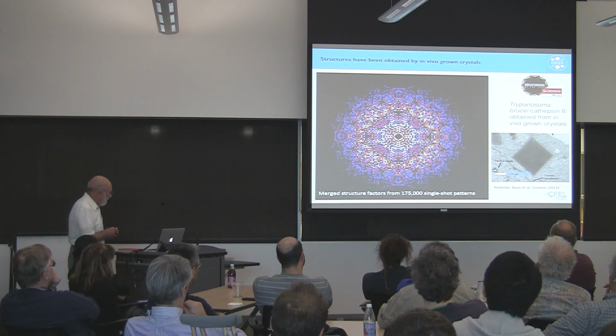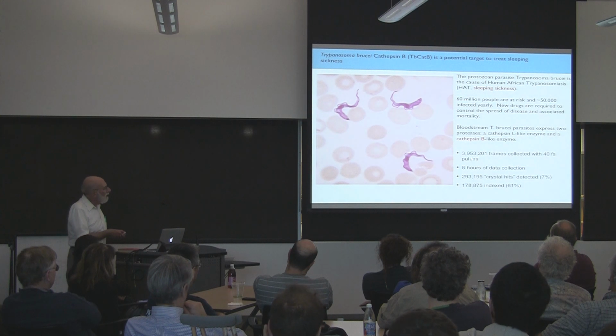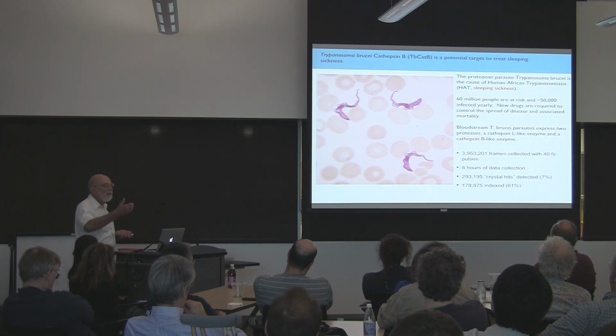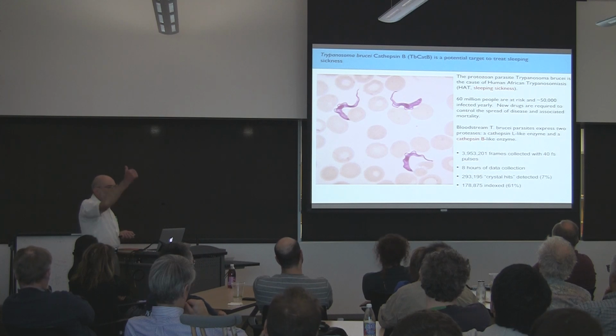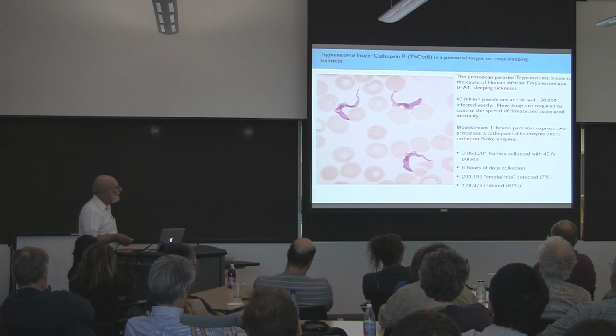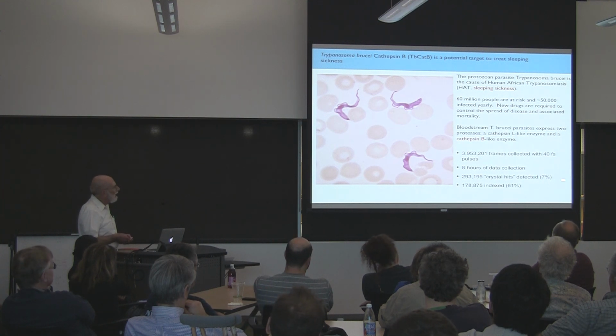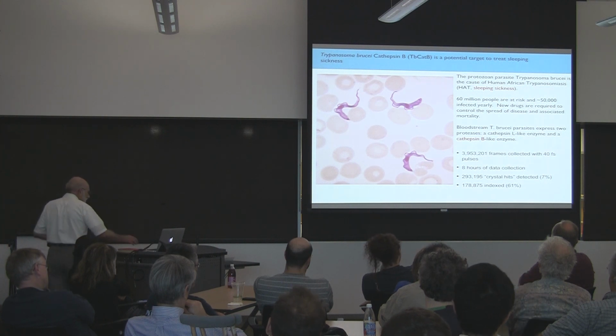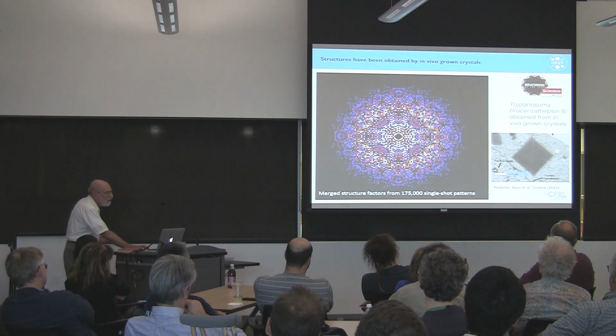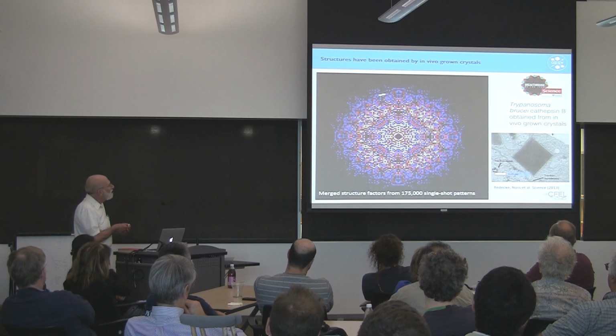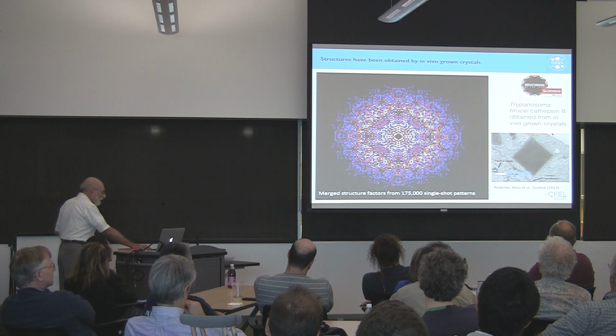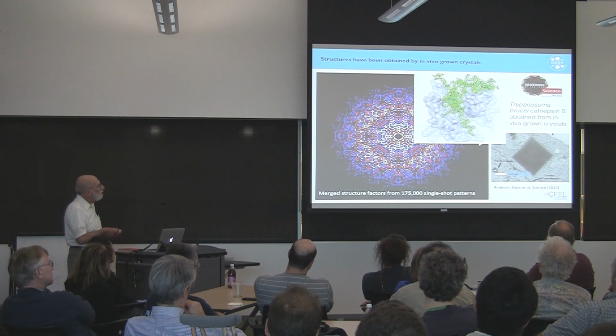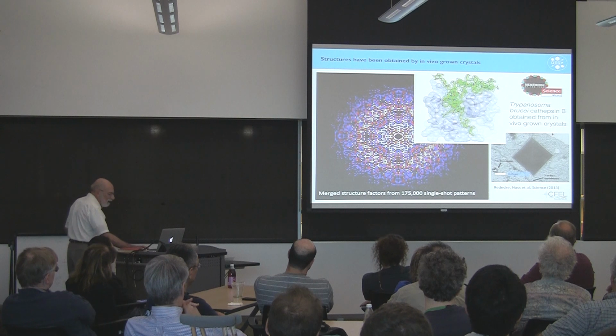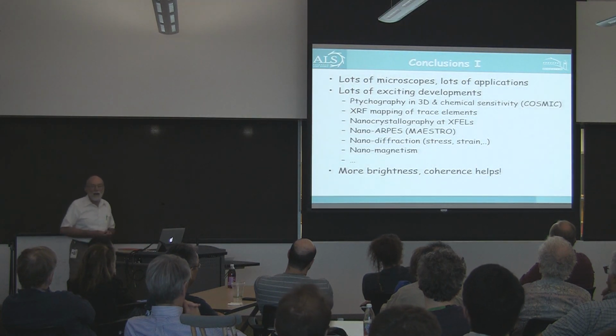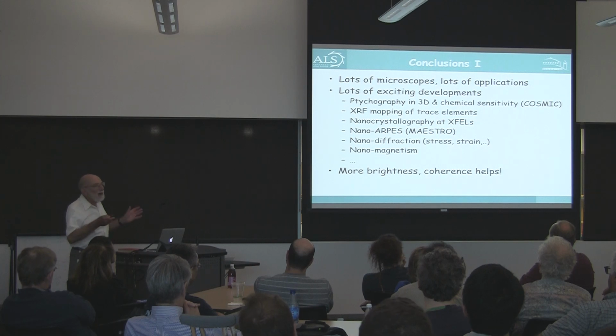And based on some millions of these shots of free-electron lasers on the injected nanocrystals of this protein, they were able to collect some 300,000 hits in an 8-hour time at the LCLS to generate a diffraction pattern that you can see here. And on the basis of the diffraction pattern, they were able to reconstruct the molecular structure, which to me is an amazing achievement. So my time is pretty much up.